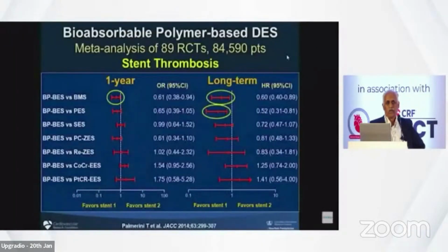Now, people said, why keep the polymer? Why biocompatible? We'll degrade it. So you use a polymer which gets degraded. They typically use PLGA that gets metabolized to carbon dioxide and water. So after 3 to 6 months, the polymer just disappears. So there's no problem with the polymer. Once the healing occurs, it is as good or as bad as a bare metal stent after the healing process. So there's no further restenosis, but you get the result.